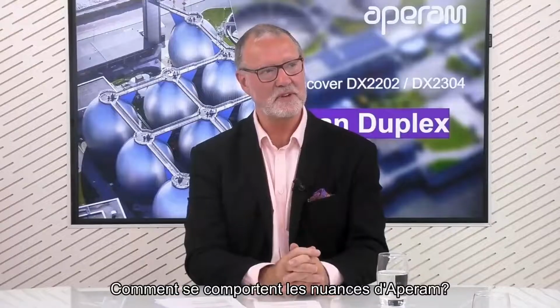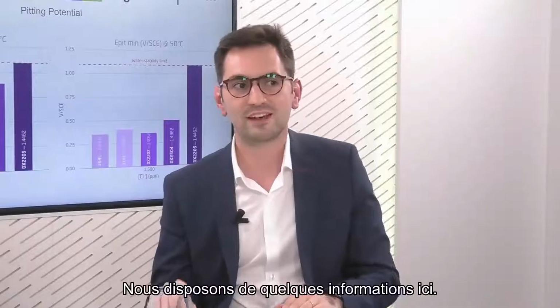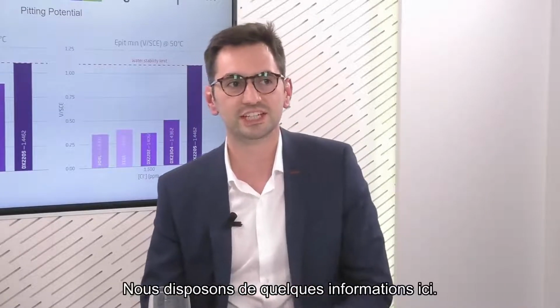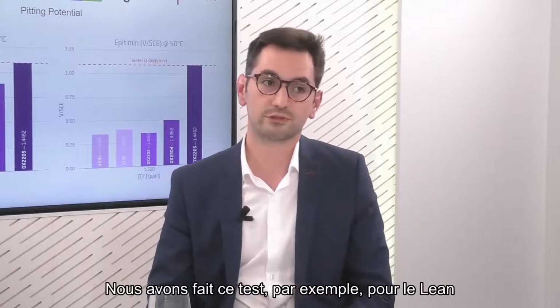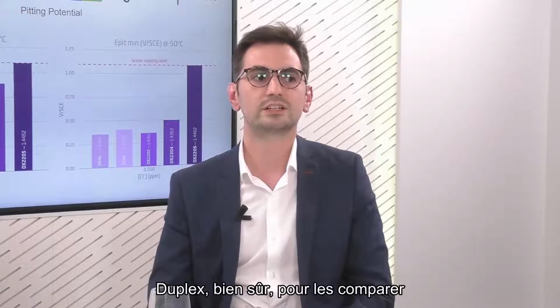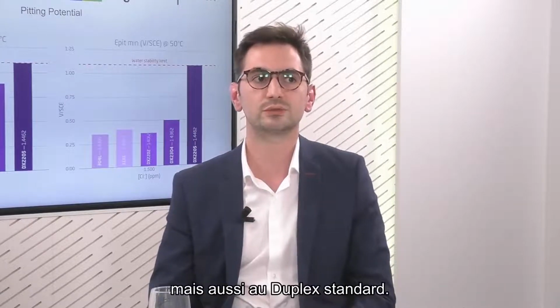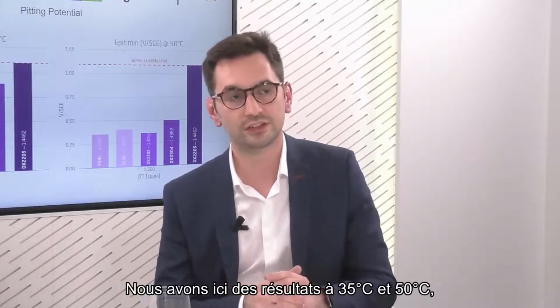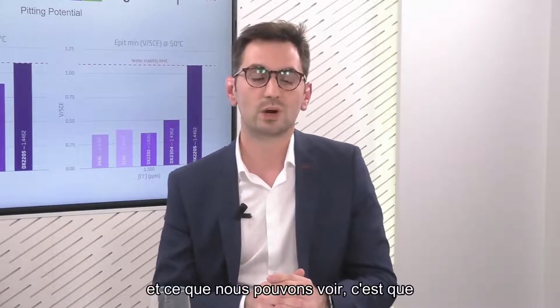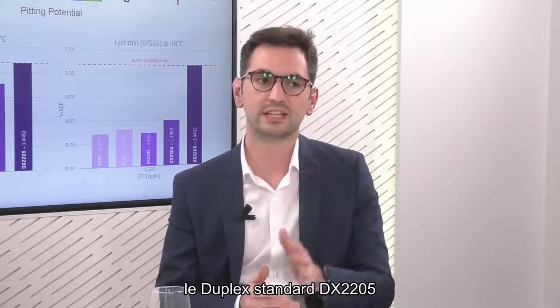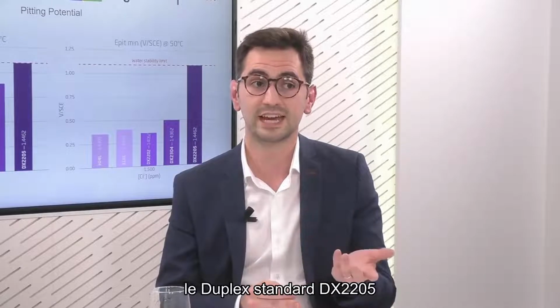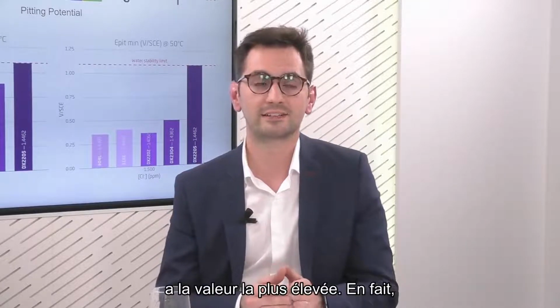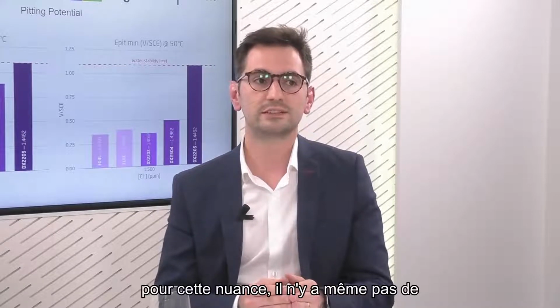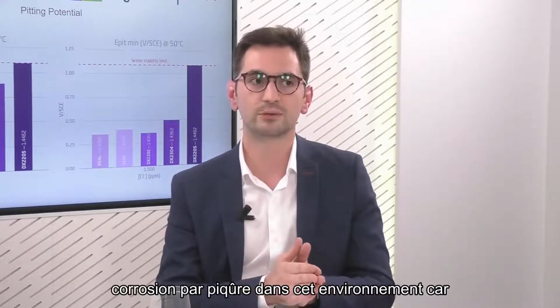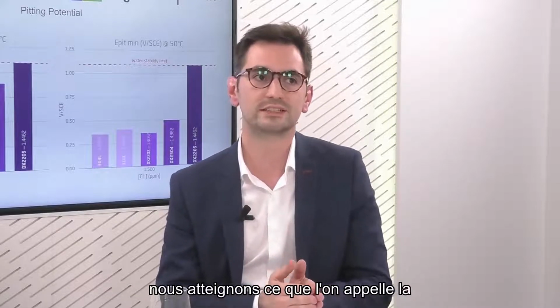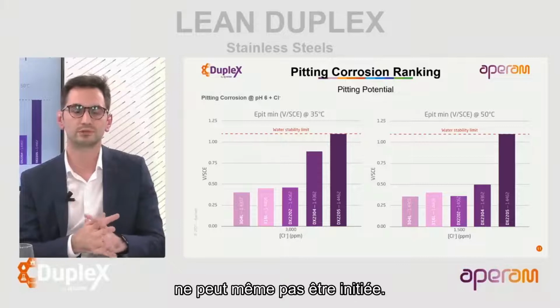And how do Aperam's grades perform? Okay, so we have some information here. We did this test, for example, for Lean Duplex, of course, to compare them to the austenitics, but also standard duplex. Here we have results at 35 and 50 degrees Celsius, and what we can see is that the standard duplex DX2205 has the highest value. Actually, for this grade, you don't even have the pitting in this environment because we reach what is called the water stability limit, so the pitting corrosion is not able to be initiated.